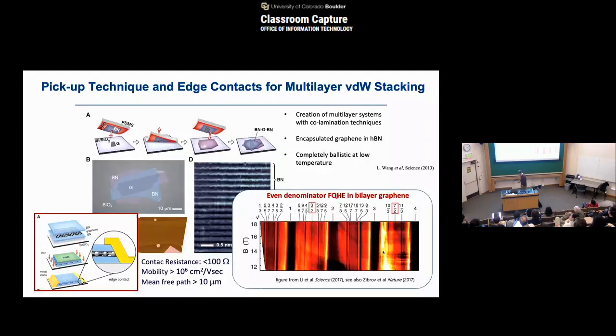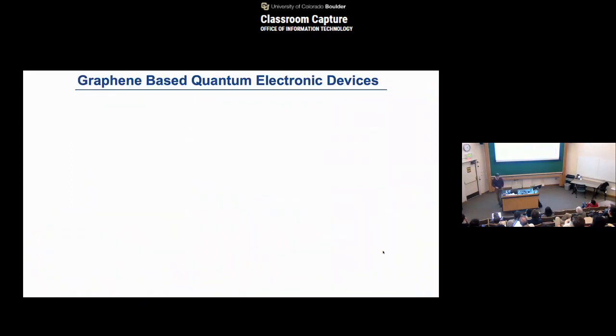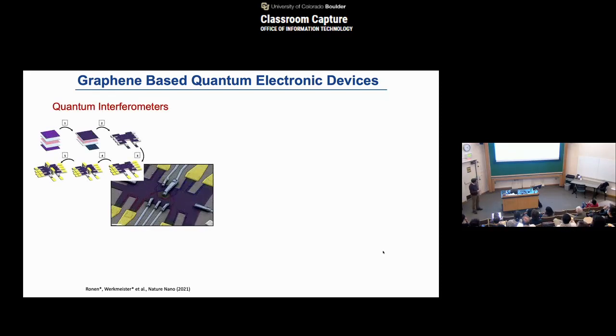For example, nowadays when you put graphene in between boron nitride, you get a high quality sample, as you're seeing here, which allows the following type of experiments. You can treat it as if you have semiconductor heterostructures, and you simply apply all the methods that we learned from gallium arsenide and repeat them here. So in this example, we start with the stack and make the contacts and make the etchings and make the local top gate structures.